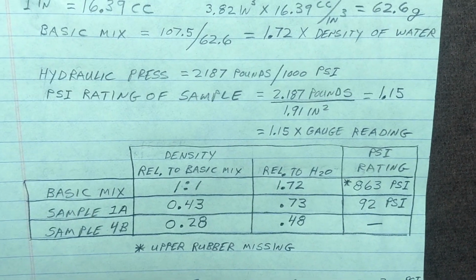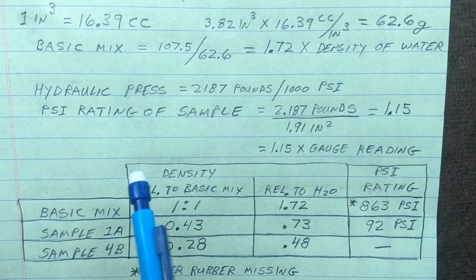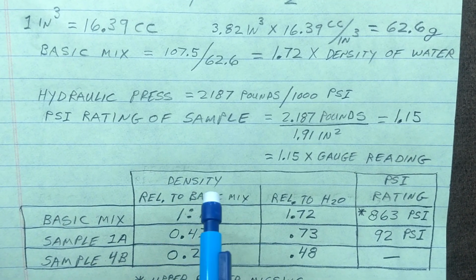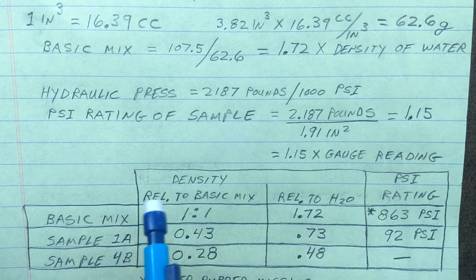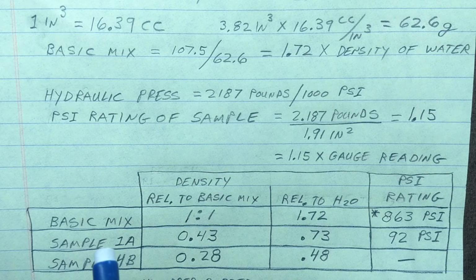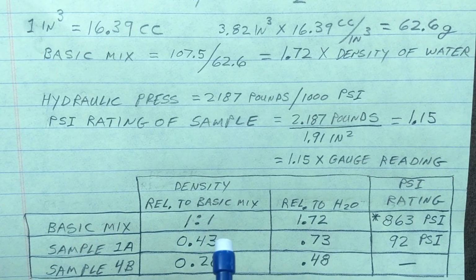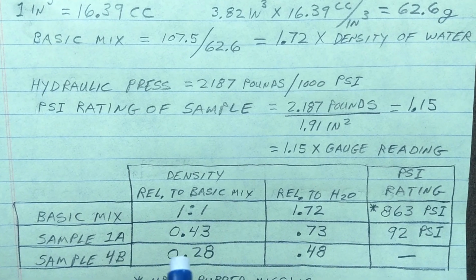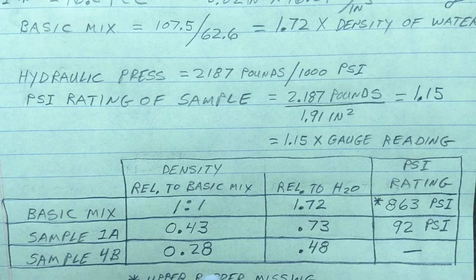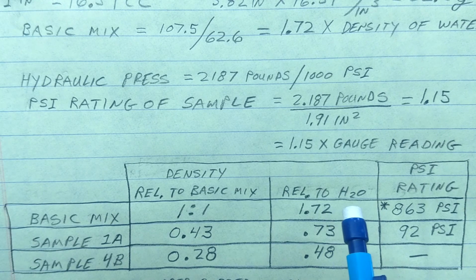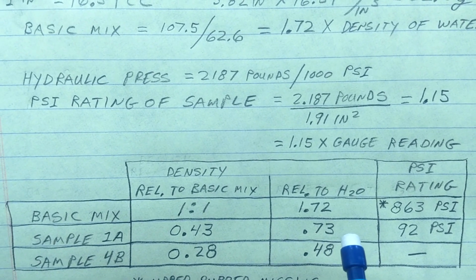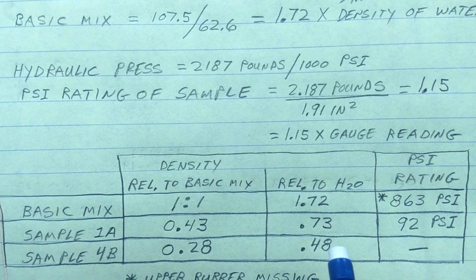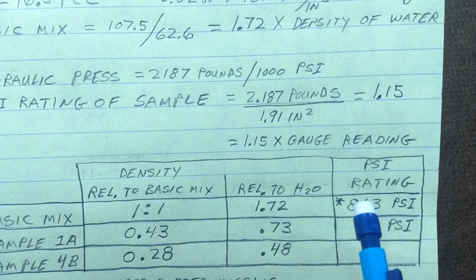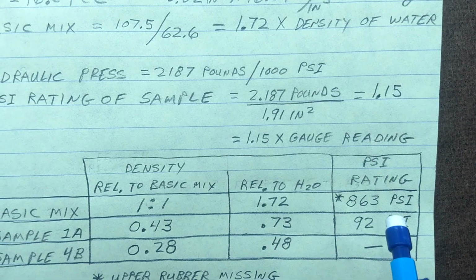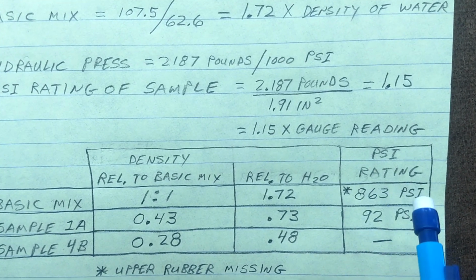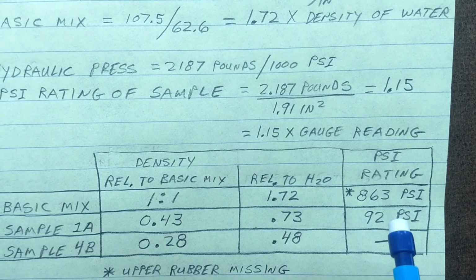So here's kind of a summary of what we ended up with. The density of each sample relative to the basic mix, well, of course, it's 1-to-1 for the basic mix. Sample 1A was 0.43 times the density of the basic mix, and sample 4B was 0.28. Now, relative to water, the basic mix was 1.72, sample 1A 0.73, sample 4B 0.48. So the PSI rating that we managed to get on two of the samples, the basic mix was 863 and the sample 1A was 92.